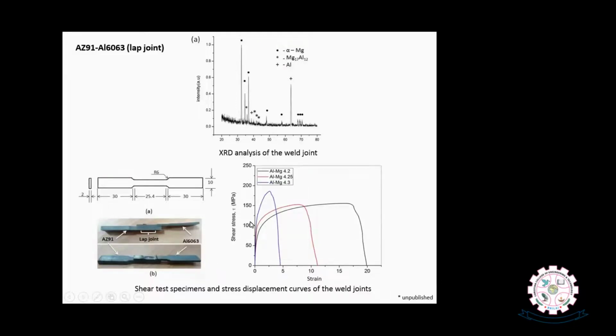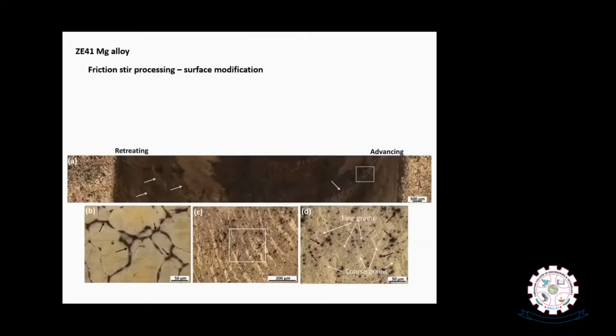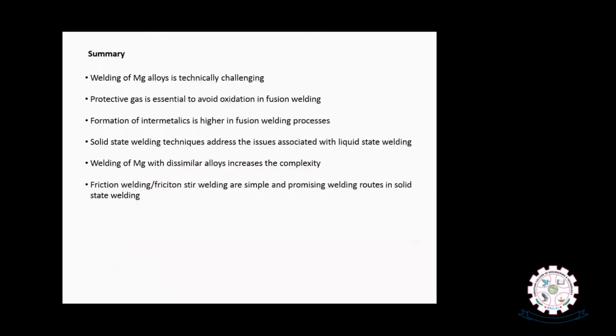The shear stress was found to be higher with the higher penetration, whereas the percentage elongation decreased with the higher penetration. So this can be attributed to the decreased length of the weld joint with the increased penetration of the tool. And another magnesium alloy, having zinc as well as rare earths as the constituting alloying elements, was processed by friction stir processing. That is another solid state processing technique developed from friction stir welding, and the properties were evaluated.